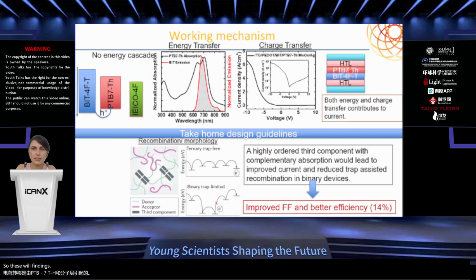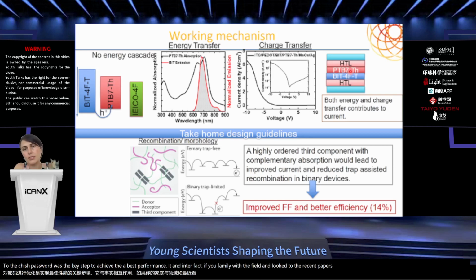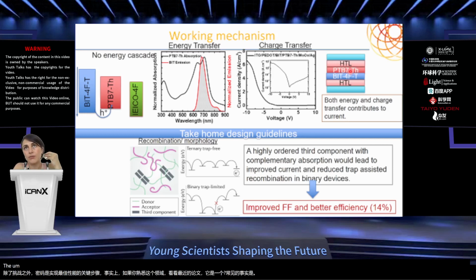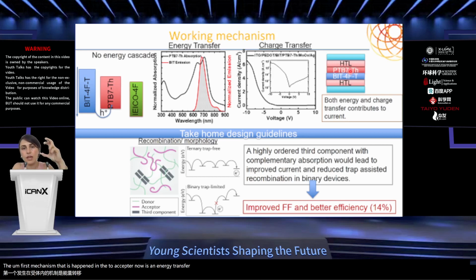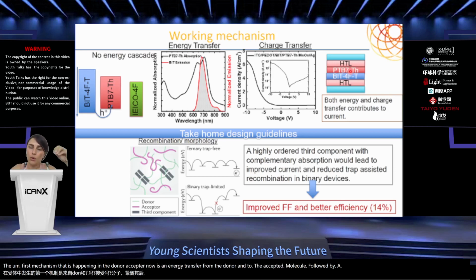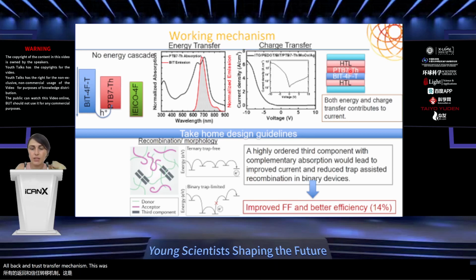So these two findings made us think that if you would like to design an efficient ternary device, in this case our performance was 14%, you need to combine all these parameters along with energetics and morphology, but also an energy transfer, additional to the charge transfer, was the key step to achieve the best performances. And in fact, if you're familiar with the field and look at the recent papers, it's now a common fact that the first mechanism happening in the donor-acceptor is an energy transfer from the donor to the acceptor molecule, followed by a hole back and a charge transfer mechanism. This was very, very interesting back in time.